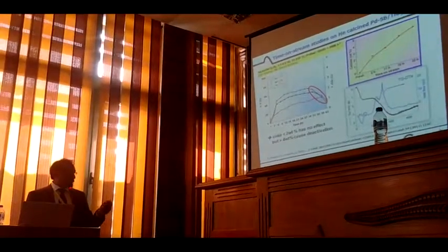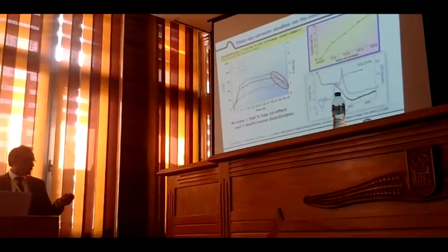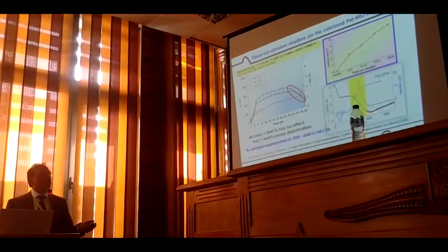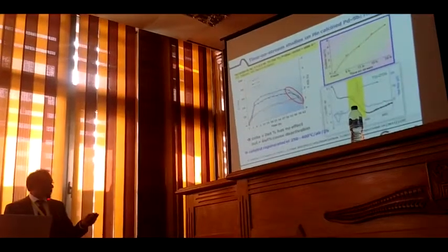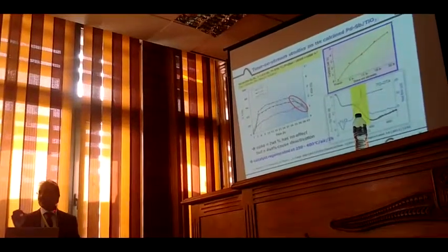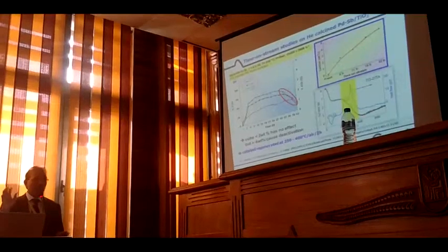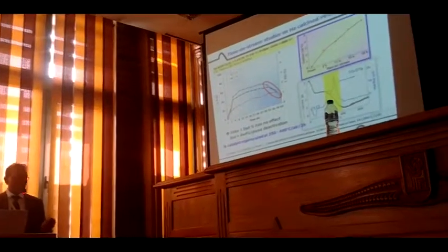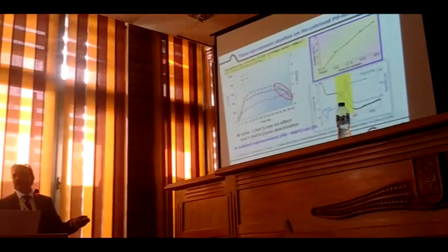So based on this, we took the spent sample where we have coke. We did thermogravimetric analysis, TG, where you can see the coke is removed in the temperature range from 200 to 400 degrees centigrade. And the coke is going in 2 steps. That gives hints that you have 2 types of carbon species. One is a carboxyl group on the surface, and the other carbon is incorporated in the palladium lattice. But anyway, we have to select the temperature for regeneration between 250 and 400.